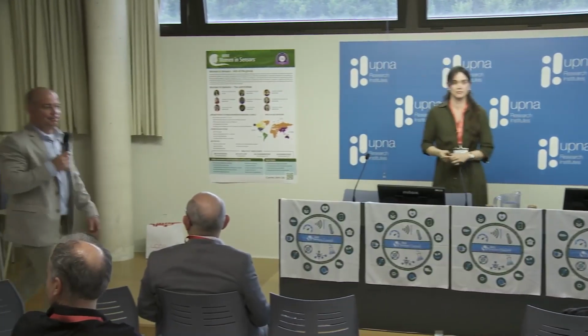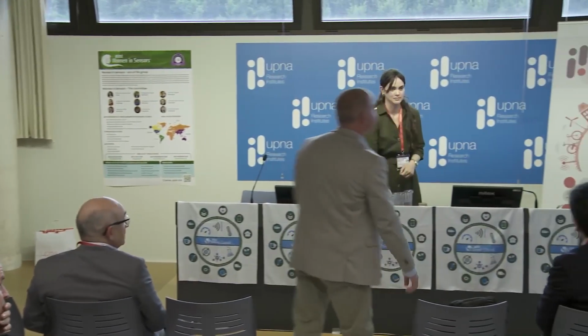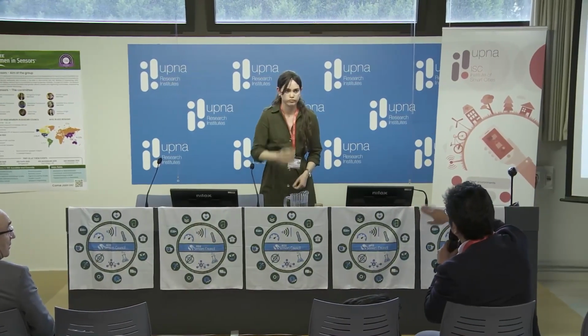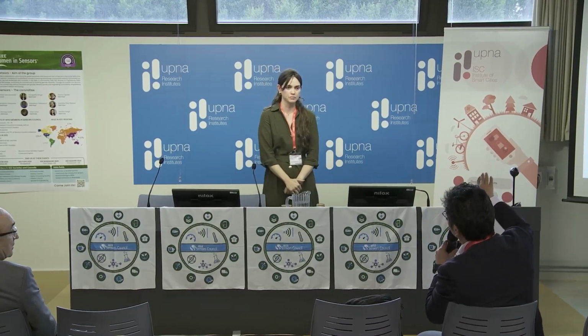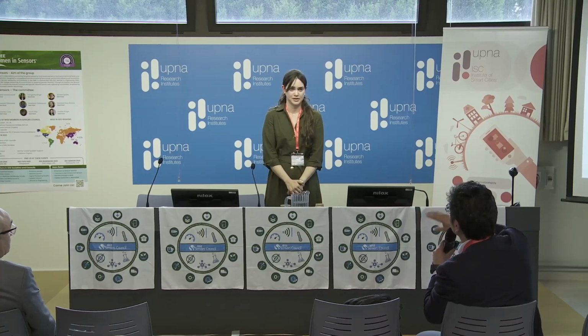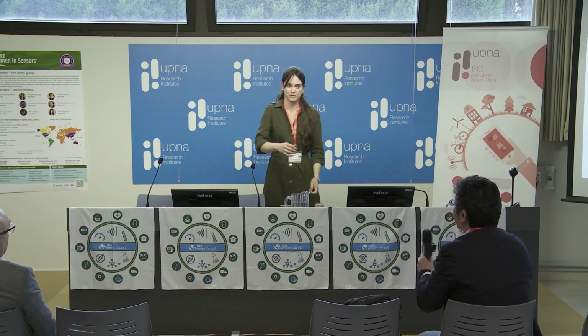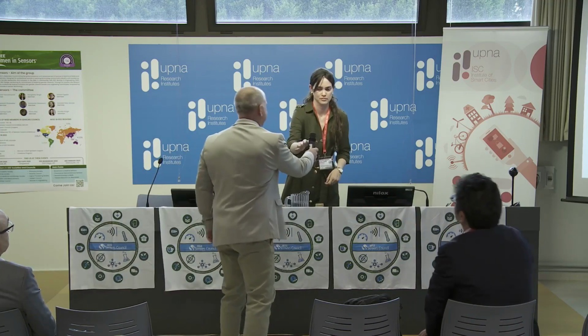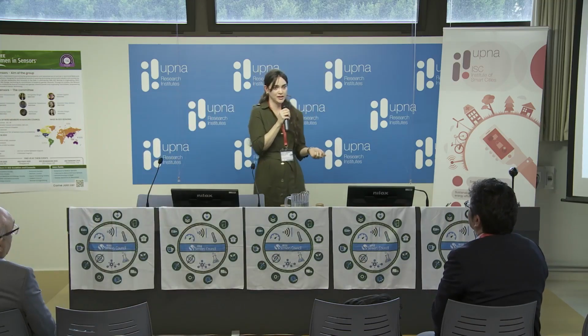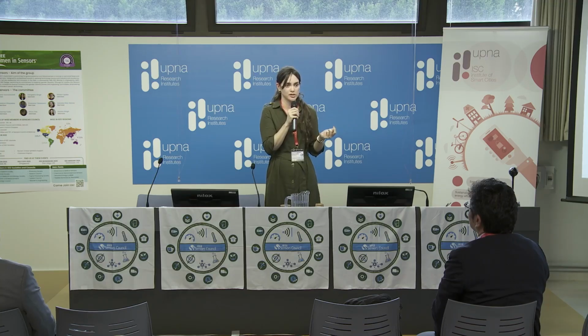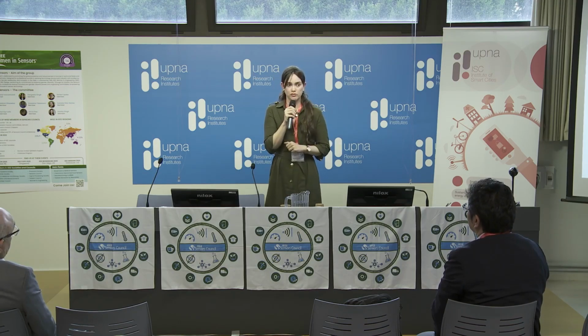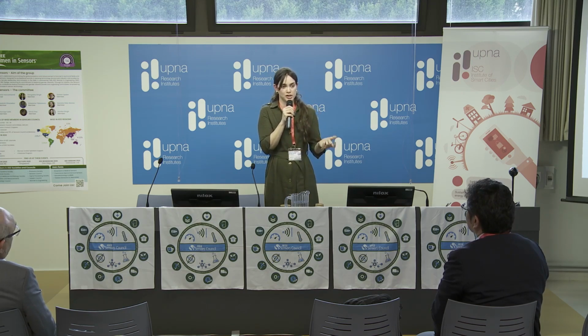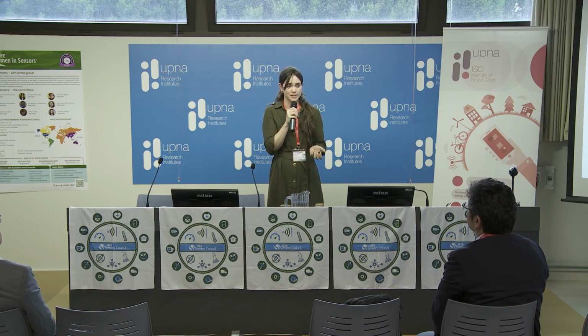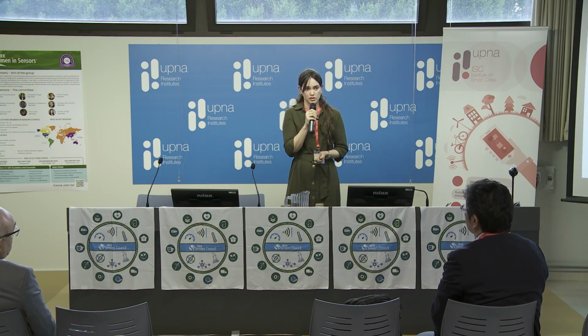Okay, no more questions? Thank you very much. So we observed hysteresis of the sensor. Can you explain the mechanism of that? The reason of that hysteresis? We think that the hysteresis in this case between both cycles, the heating cycle and the cooling cycle, could be explained by the expansion and contraction of the crystalline network of the quantum dots. These processes are not identical, and that's why they are not reversible. That's why those differences occur.